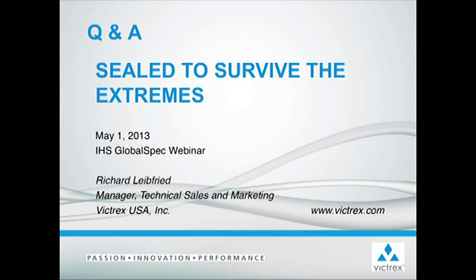How do you decide when to go with reinforced PEEK, glass or carbon filled, versus unfilled PEEK in a sealed backup ring? That's a great question. You really need to look at the key engineering requirements, VICTREX calls these KERs, to perform as needed in the end-use application. This means considering the environmental requirements like continuous exposure to high temperature, chemicals, and wear. You also need to consider static and dynamic loading, as many seals will experience fatigue due to thermal or load cycling. Finally, you need to establish the expected design life for the seal and consider the effects of creep.